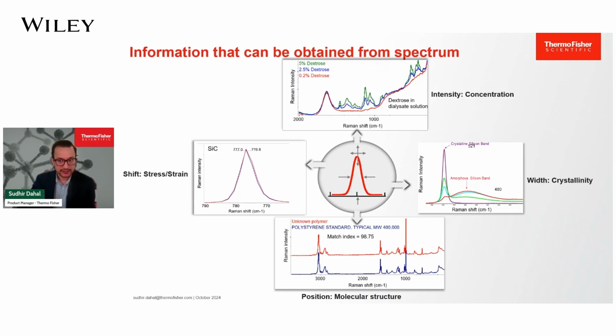At the center of the slide, as you can see, you'll observe a simple curve with a peak that serves as an illustrative example. So beginning with the bottom image shown by the red arrow, this highlights the importance of peak position along the x-axis. The location of various peaks on the x-axis provides critical information regarding the molecular structure. In essence, the appearance and positioning of these peaks are instrumental in sample ID or molecular identification. Now, at the top, the spectra illustrate the relationship between intensity, which is shown on the y-axis, and concentration. An increase in intensity corresponds to higher concentration of the substance and vice versa.